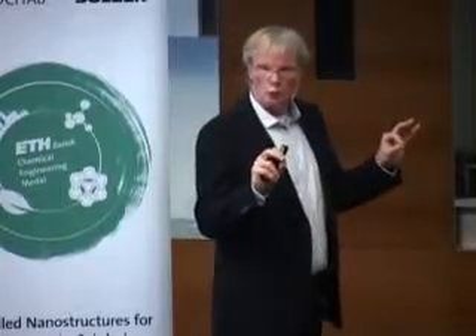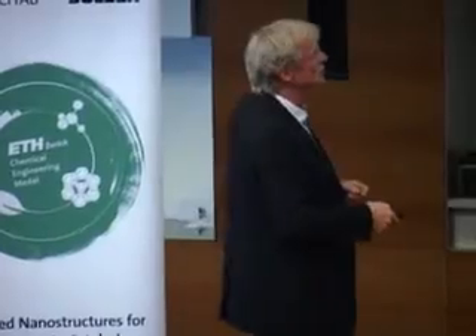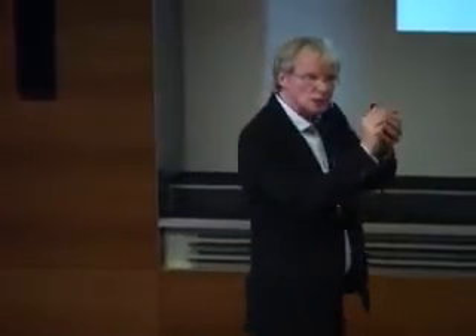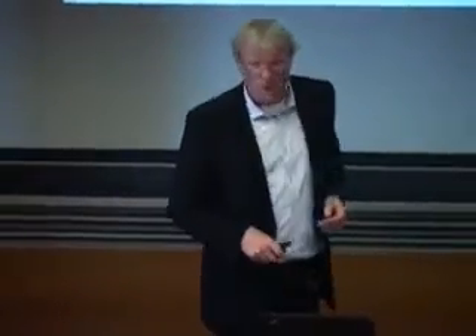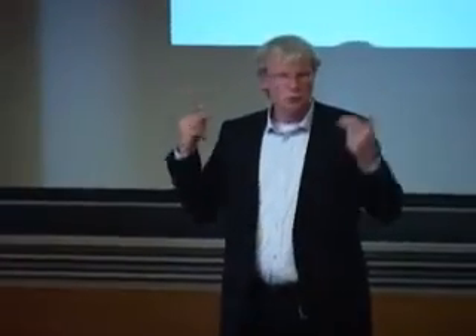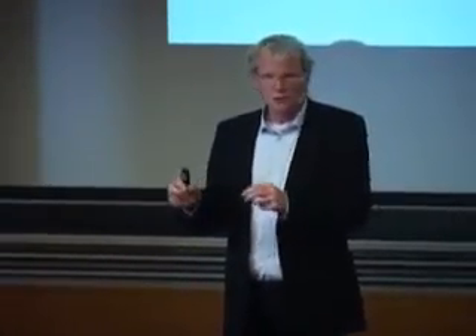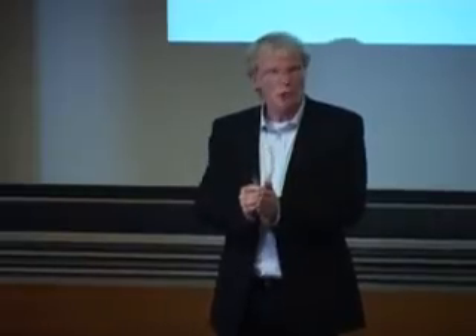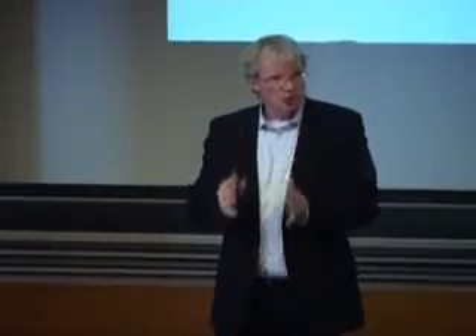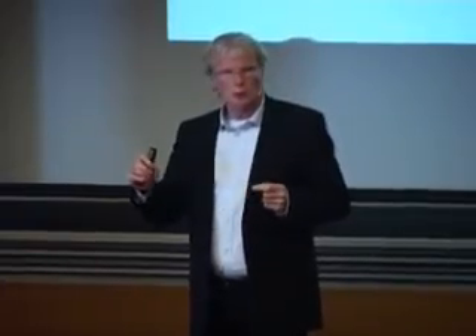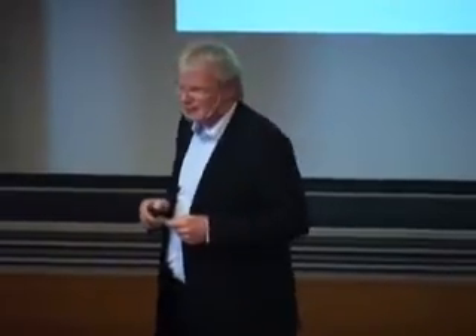So this agrees almost too nicely. This is really a very high stabilization. And these commercial catalysts lose about 50% of surface area and particles. So this encapsulation pathway indeed works very well. I don't show the results, but we have translated this to a real fuel cell catalyst. The people in Duisburg at ZBT have really built fuel cells from these catalysts, and we see the same behavior in a real-world fuel cell.